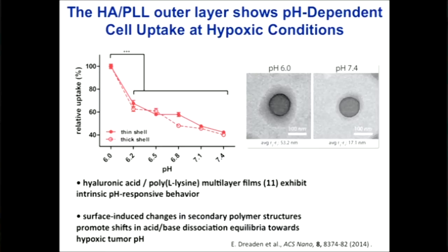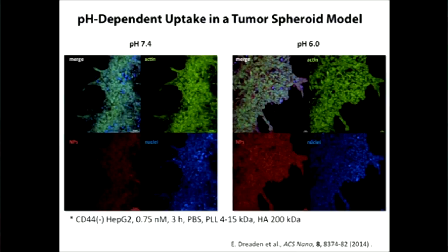This is just a way of measuring this. We can take a tumor spheroid model. This is just clumps of cells that are made up of tumor cells. And we can stain our nanoparticles red here. The nuclei are stained blue, and they're always present. And we've stained for actin, also always present. But we're also looking for hypoxia in these systems. So in this case, we can see that at pH 7.4, we don't get much nanoparticle accumulation. But at pH 6.0, we really light up. We get a lot of accumulation in these tumor spheroids.